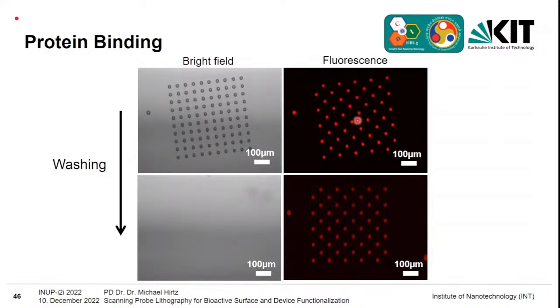Also, these droplets that you don't see here are biotinylated now. If you wash everything away, then in bright field you will not see anything anymore, because there is only a monomolecular layer remaining. But if you look at fluorescence, you will still see the nice array as before. You can see that it's a little bit less fluorescent, but that's because now we're really looking at only a monolayer of the molecules and not a whole droplet anymore.